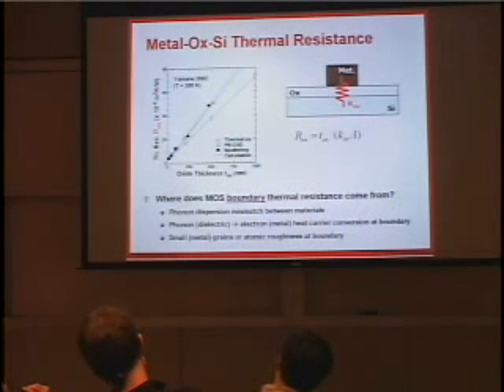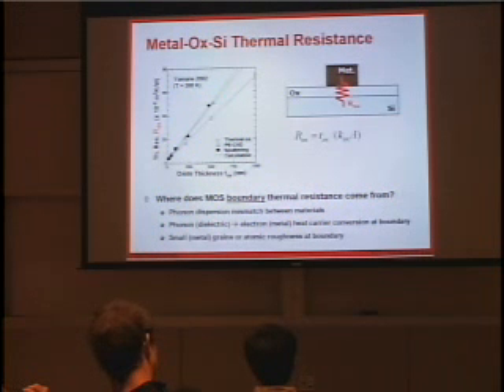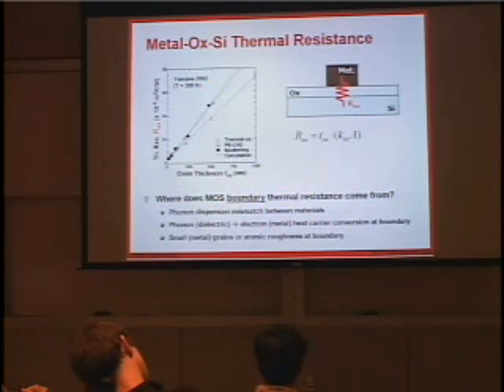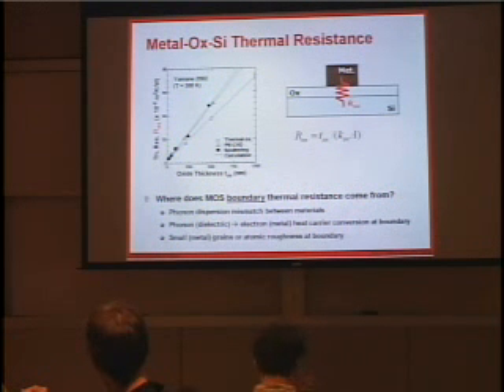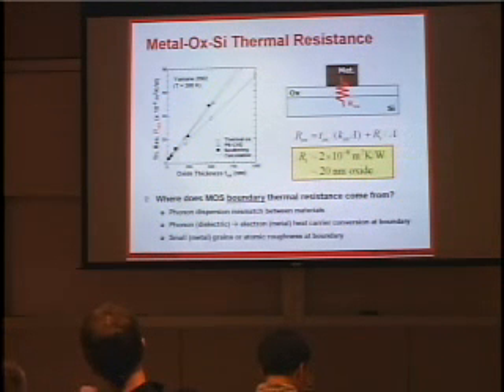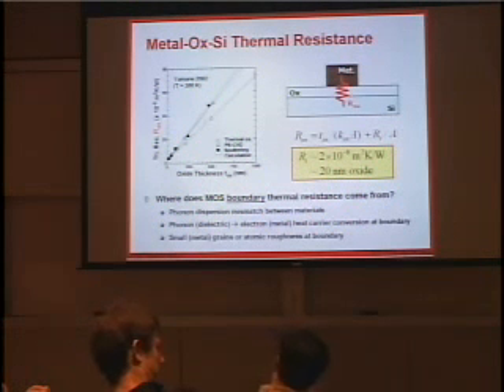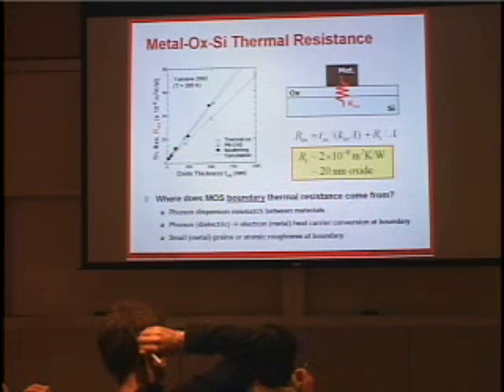The other thing that I'd like to look at is when you put a metal gate on top of an oxide, on top of a thin oxide. The measured thermal resistance of that thin oxide is actually larger than you would expect by simply using the formula: the thickness of the oxide divided by the oxide thermal conductivity times the area. And what several research groups have found, and the data is compiled on this one plot, is that there's an extra component to the thermal resistance of these metal oxide semiconductor structures.